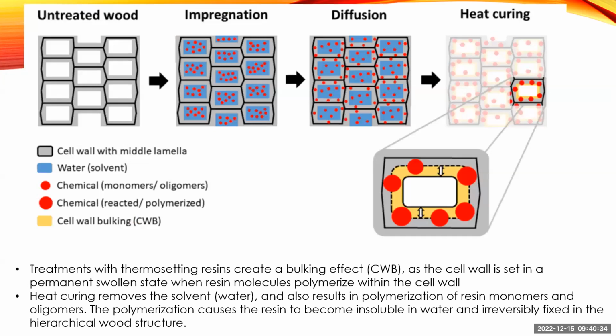Similar to other impregnation modification techniques, treatment with resin creates a bulking effect, as the cell wall is set in a permanent swollen state when resin molecules polymerize within the cell wall. Heat curing removes the solvent and water, and also results in the polymerization of the resin monomers and oligomers. This polymerization causes the resin to become insoluble in water and permanently fixed in the wood structure.